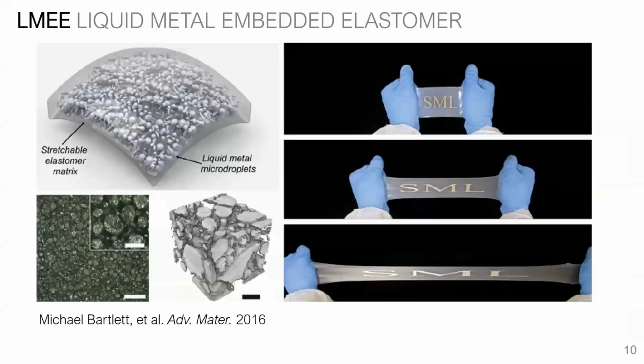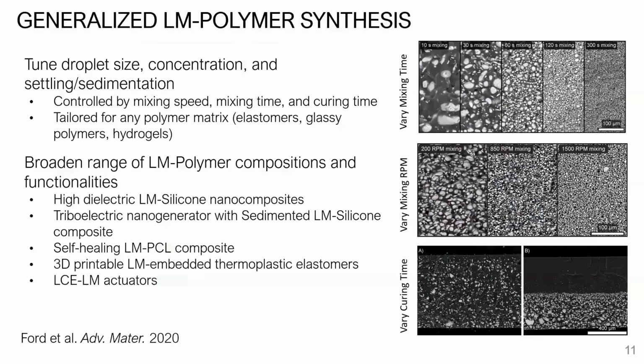That led us to look at a different architecture for blending liquid metal and elastomers, in the form of suspensions of micro- and nanoscale droplets. We call these liquid metal embedded elastomers. You have these metallic inclusions. They're liquid, so they can stretch and conform to the surrounding material, but they're metal, so they can endow these materials with either high electrical conductivity or high thermal conductivity. To achieve high electrical conductivity, we have to have really large concentrations of these droplets, on the order of 50% by volume, or 85 to 90% by weight.